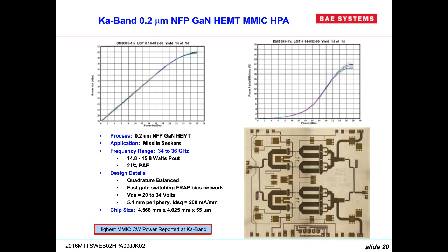And there still is a problem with silicon, that the inherent RF performance of the transistor is not quite as good as something like silicon carbide, probably due to lattice and buffer constraints that appear in a silicon-based process that don't appear in a silicon carbide process.